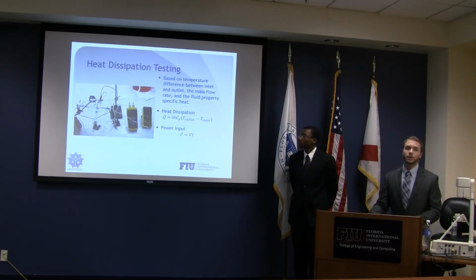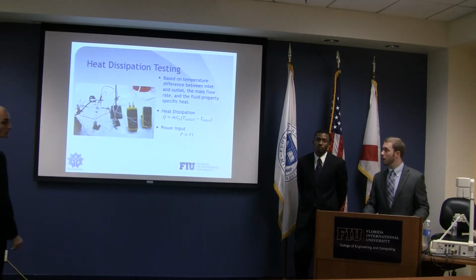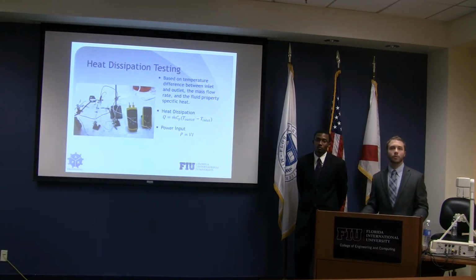The next set of testing we did was the heat dissipation using a fluid medium. And yes, he's passing around the devices that we used for this test. It essentially had the same setup. There was no embedded thermocouple between the interface, but the resistive heater was placed on top of it. A thermocouple was measuring the inlet temperature, and then 3 thermocouples were measuring the outlet temperatures.